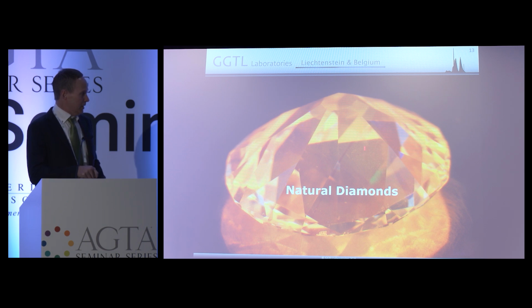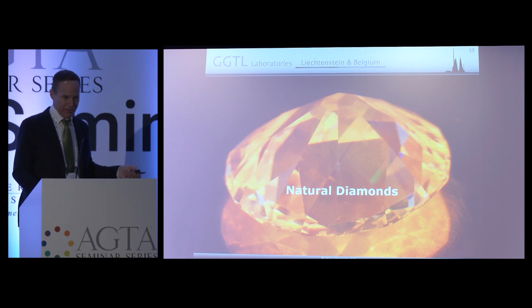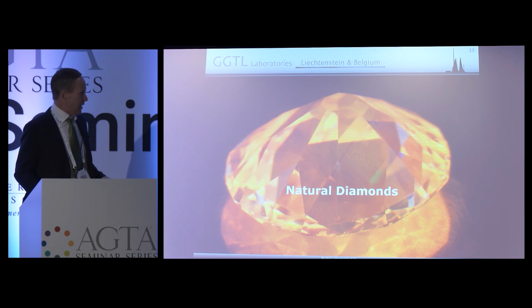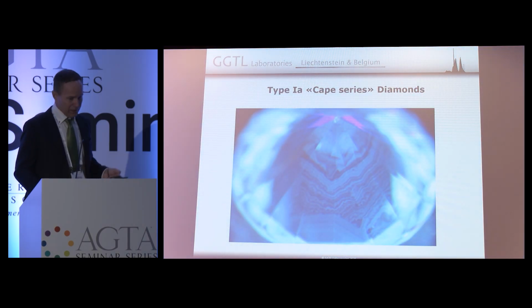Here you see these little patterns here are all dislocation networks. It's a type 2A diamond. And this has this beautiful orange fluorescence. This is very rare. You don't see that very often. You see these dislocation networks. You know this stone is natural and of natural color even. Let's look at the most common ones.